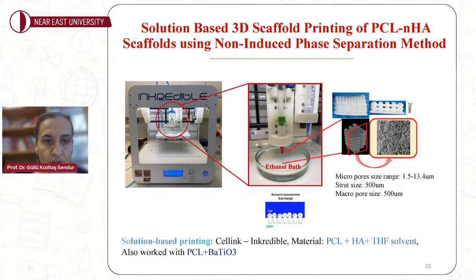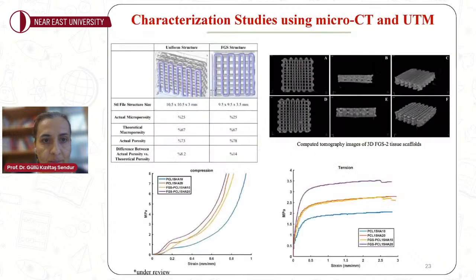Again, a view which shows that this is a nozzle-based solution-based printing, and we work with, as I said, PCL and HA. We use THF as a solvent and ethanol as the non-solvent. I would also like to note that this method has been proven to work recently with piezoelectrics, and we're currently on the way to publishing that work as well.